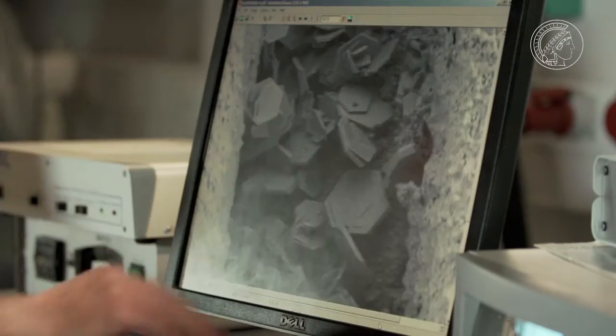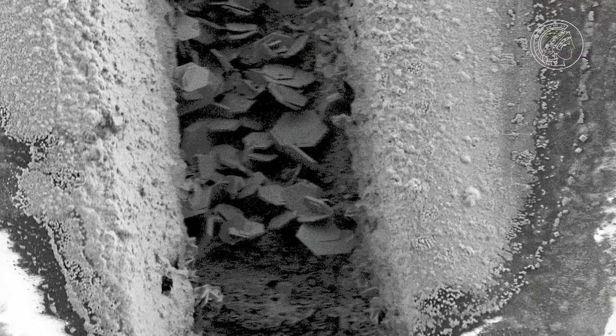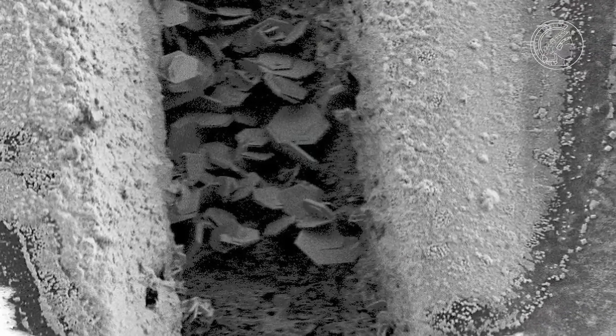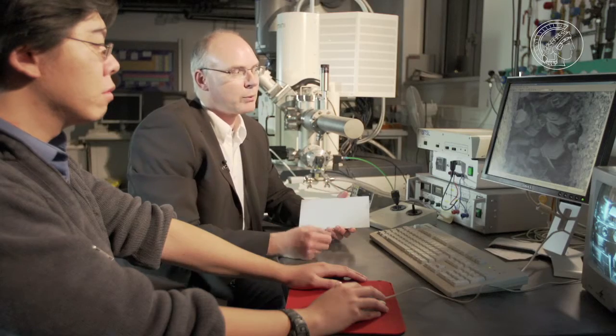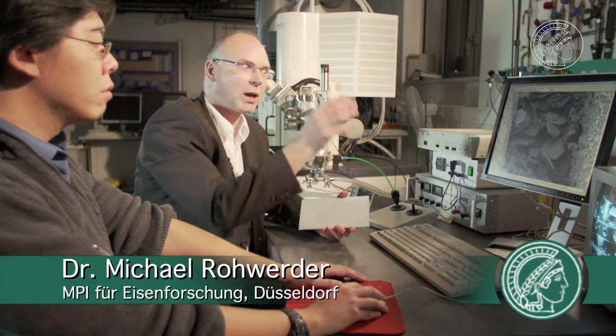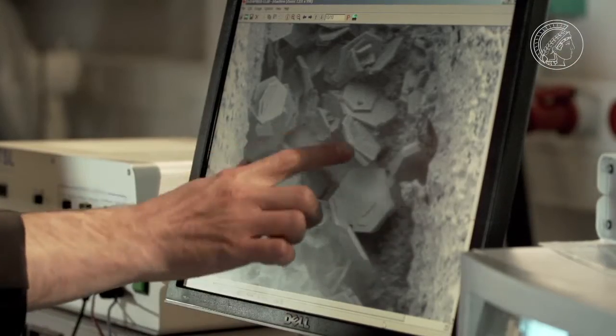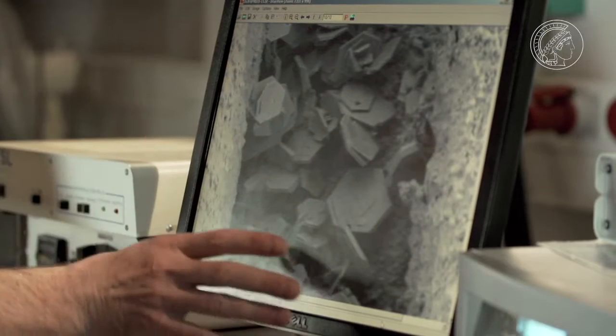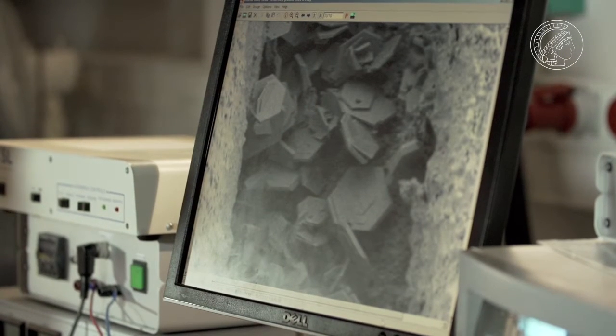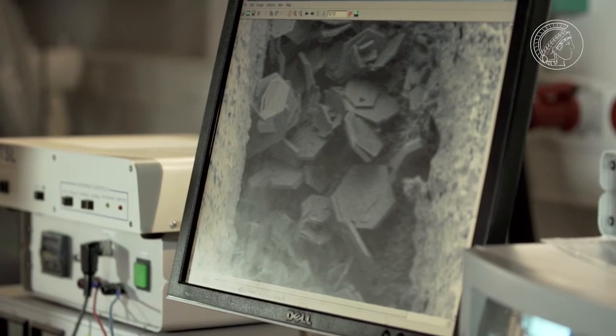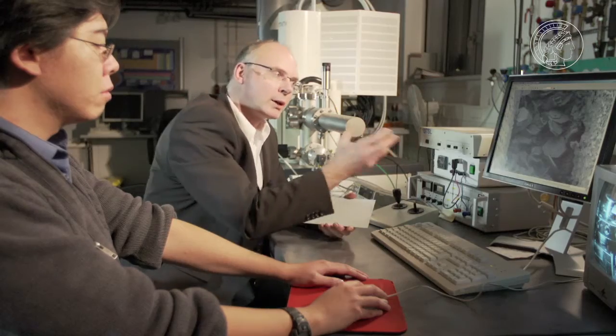And if we have a scratch in the zinc layer, the zinc will disintegrate. It sacrifices itself to protect the steel. That is the first function. The second function is that the corrosion products condense on the steel, as we can see clearly in these zinc oxide platelets, which have condensed on the steel and formed a second skin. In principle, thus providing a first protective mechanism. And that is the basis for the corrosion protection using zinc.